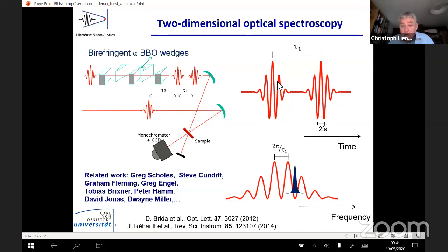And you see, and you know this from your undergraduate courses already, that such a double pulse structure essentially gives rise to a comb-like frequency spectrum. And that is interesting now, because you can see that by choosing tau1, you can decide whether you want to have a minimum of the electric field amplitude at the spectral position of a certain quantum emitter that you want to excite in your structure, or if you want to have a maximum. So when you tune this gradually, from small tau1 to very large tau1, you will periodically excite or not excite a certain structure. And the periodicity is given by the color of this guy.